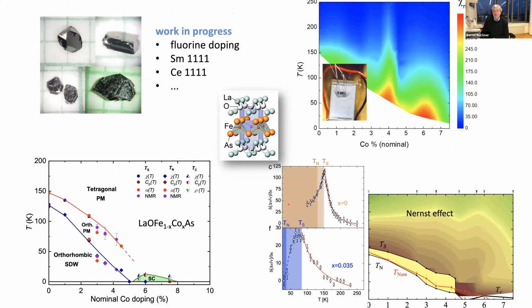Okay, that's what I wanted to tell you today. So I've presented you some, let's say, first results on this first series of single crystals. It's still work in progress. We are trying to get the fluorine doping working. We now also have systems with higher TC. I've shown you this kind of phase diagram. I've shown you this very pronounced double peak feature, which you see in the nematic susceptibility, somehow inferring that indeed nematic susceptibility is strongly coupled to superconductivity here, and it is coupled to spin fluctuations, which leads to very strange behavior in the normal state of these materials.